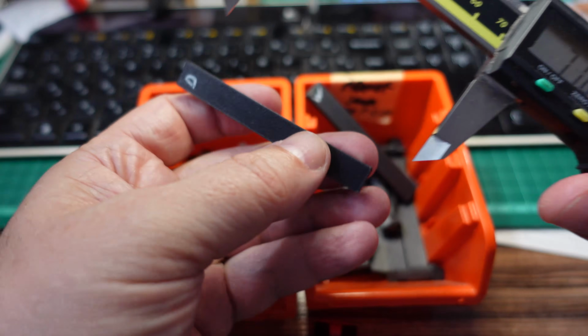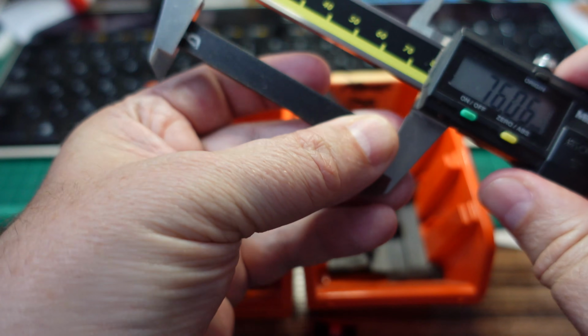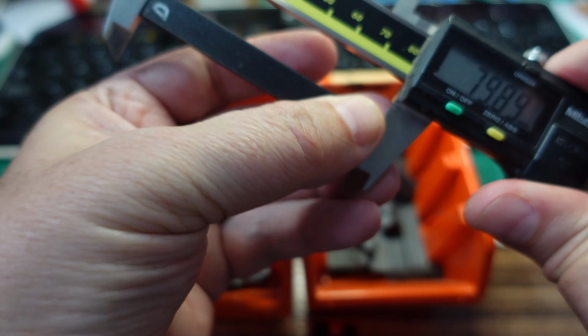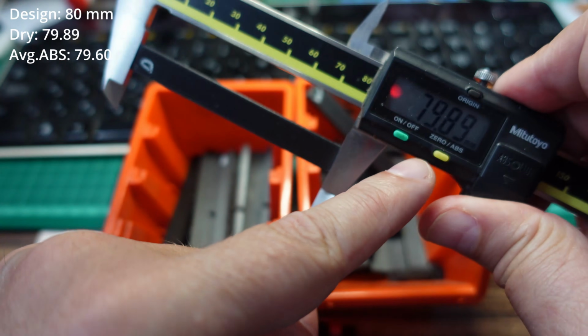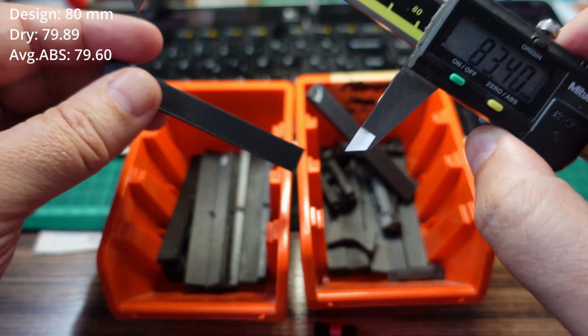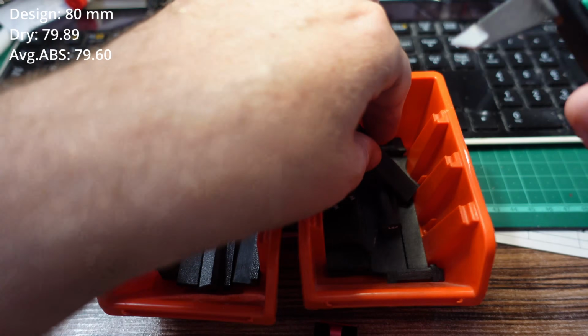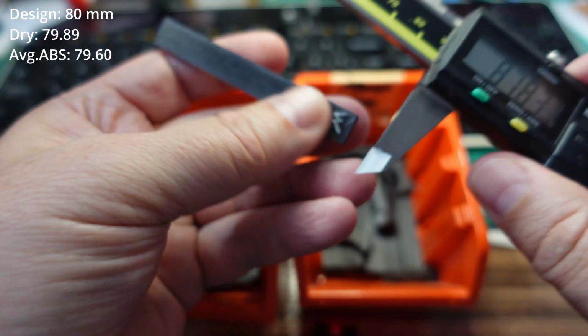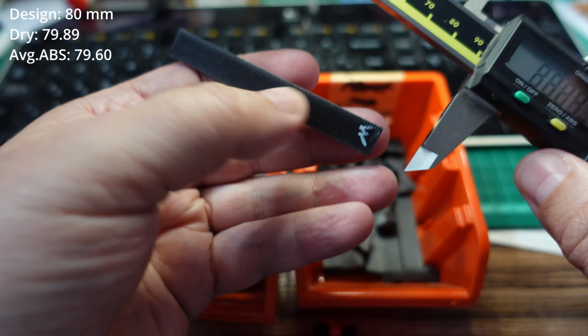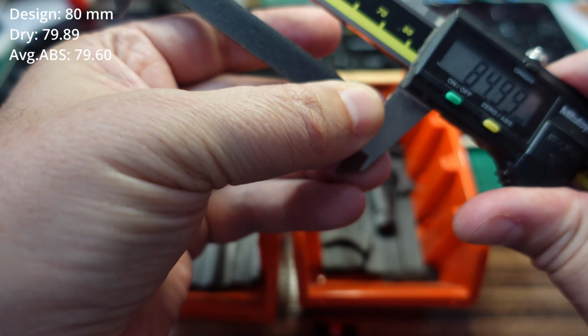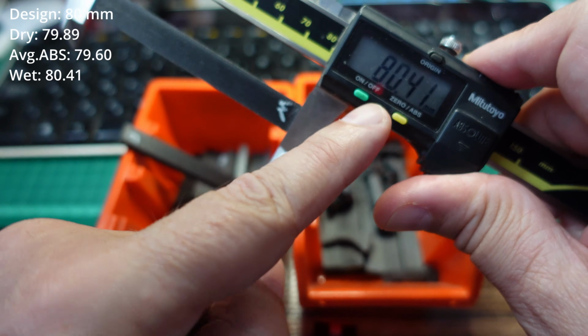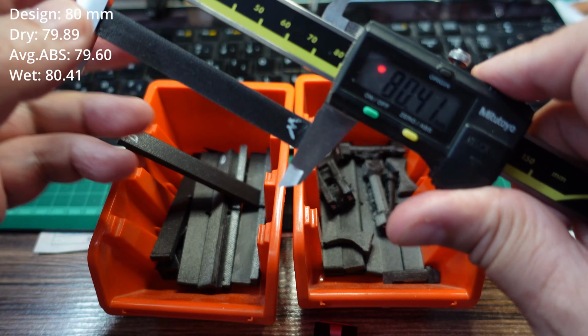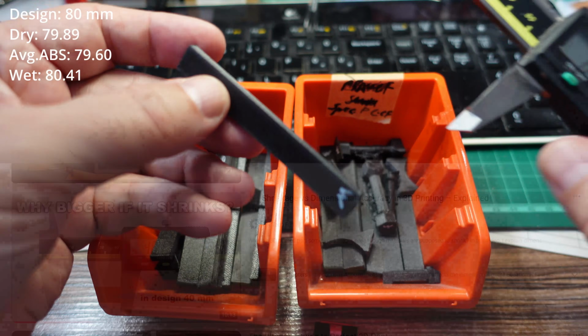Printed from dry filament. I'll try to measure above the elephant foot. And 79.89, the design length is 80 millimeters, so it has some minimal shrinking, but much smaller compared to, for example, average ABS. This was printed from wet filament, and this should be bigger because of that over extrusion. Oh yes, definitely much bigger, 80.41. Definitely this was printed from wet filament.